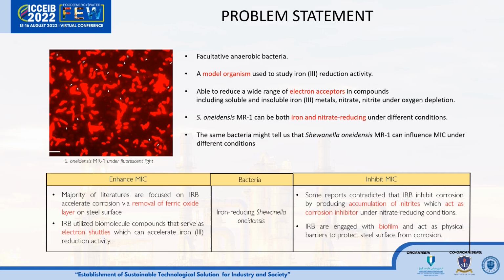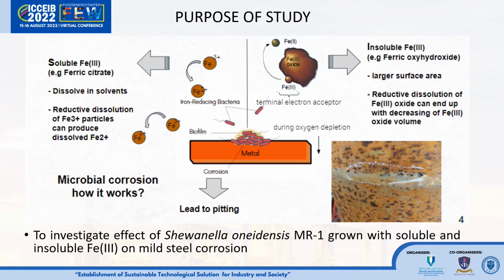Due to this, we intend to design an experiment using the same bacteria: how this facultative Shewanella affects MIC under different iron 3 reducing conditions using soluble and insoluble iron. To investigate the effect of Shewanella oneidensis MR-1 on mild steel corrosion, Shewanella oneidensis MR-1 will be grown under either soluble iron 3 using ferric citrate or insoluble iron 3 using hydrous ferric oxide, HFO.